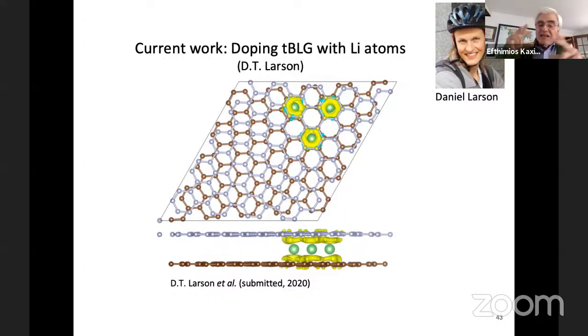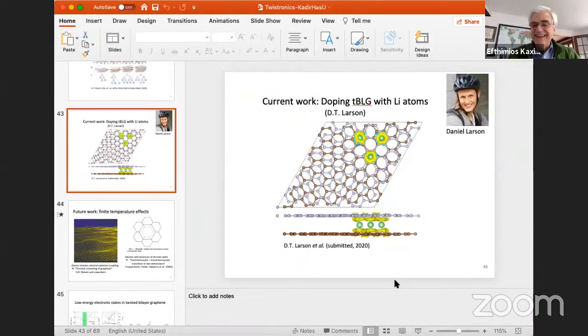So because of the relaxation pattern that I was showing you, the little mountains and the valleys, we have suggested to take advantage of that and intercalate lithium atoms, which will be stuck in small regions. And that would play the effect of impurities, localized impurities, but also controlled impurities. You know exactly where they would go. And hopefully this would lead to even more interesting behavior under full control of what you are doing, if you can control the amount of intercalation and the place where these intercalant atoms end up, which is dictated by the relaxation pattern. So if you want to work on this type of impurities, I'd be very happy to talk to you, very interested in talking to you more, Nihad.